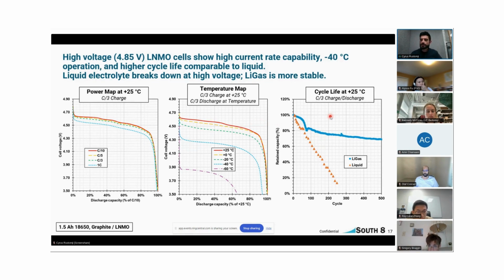And the cycle life is really interesting. Because it operates at a higher voltage, your liquid electrolytes always fail very quickly because your standard carbonate-based electrolytes do not withstand that high voltage, and they begin degrading and the cell will fail very quickly. So you can see within tens of cycles, you hit 80%, and then very quickly it's diminished to essentially nothing. With your liquefied gas electrolytes, on the other hand, it is a little odd.